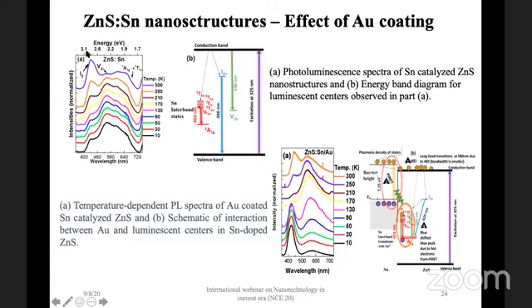Now this on the left side, top panel, zinc sulfide doped with tin PL, so without gold, is given over here, which shows a very bright, broad spectrum. So blue is very strong, and then we have a green and red, and it goes down. And this is actually a white light source, which we have predicted when we dope with a certain amount of tin, because it controls the zinc and sulfur vacancies, and it creates defects, which leads to these red and yellowish red defect states.